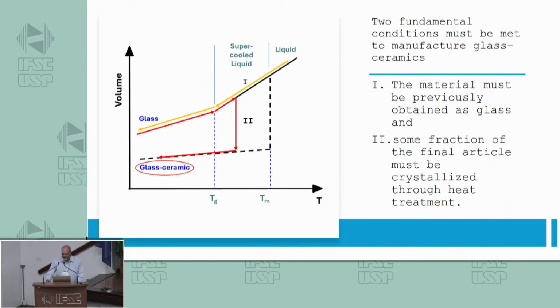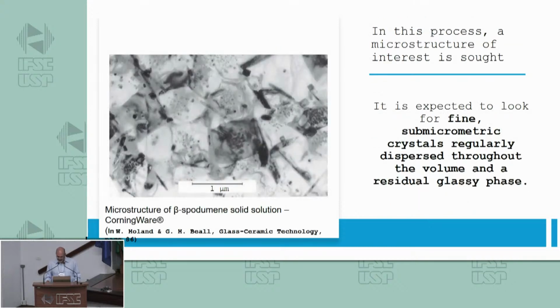So to obtain a glass ceramic, we have to achieve two fundamental conditions. We have first to get a glass, melting some raw materials above the melting point, the liquidus, and then fast cooling it below Tg to obtain a glass. And this glass is afterwards reheated above the glass transition and given enough time to crystallize, and then we have a glass ceramic if the microstructure is regular and with good properties. In this process, a microstructure of interest is sought.